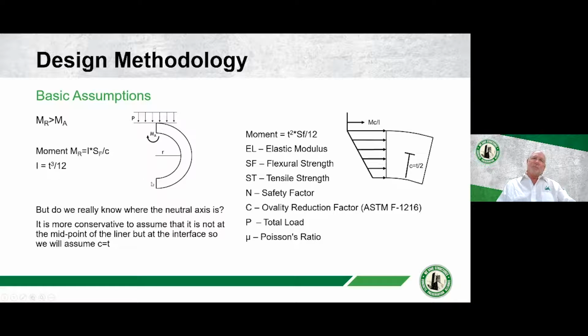What you've got is a cylinder here, and based on the cylinder, you get this moment, the moment resistance, which is the modulus of the material times the flexural strength of the material divided by the distance to the neutral axis. For simplicity and conservative, what we do in our design is we take the neutral axis equal to the thickness. So this gives us a built-in almost 2-to-1 safety factor. It also creates an easier calculation. So what we'll end up for a resisting moment is that the thickness squared times the flexural strength of the material divided by 12 will get us the resisting moment of the liner that we're installing.